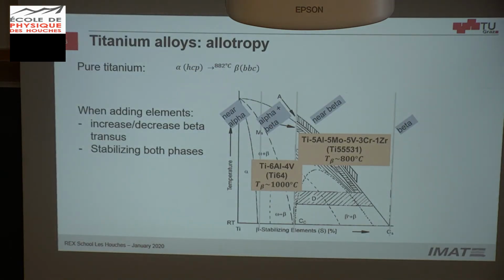So the most important thing in titanium alloys, it's very similar to steels. If you know something about steels, then titanium is easy peasy. It's even easier because we don't have any eutectoid reaction. But we have this allotropic transformation. We have an HCP at low temperatures, which is not close packed. It means it's a bit longer in one axis. It means we have a crystallographic structure that is not that bad for deformation. It also has some other slip systems that activate. And by increasing the temperature, then we transform into BCC. This is a BCC, sorry. So BCC, here is wrong.